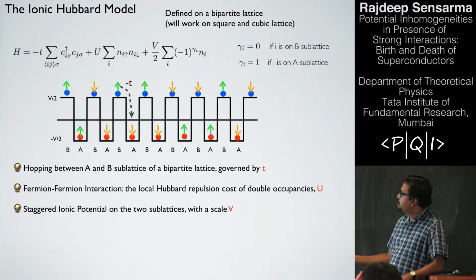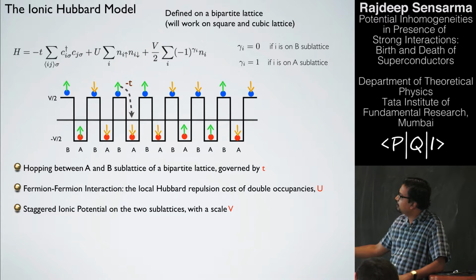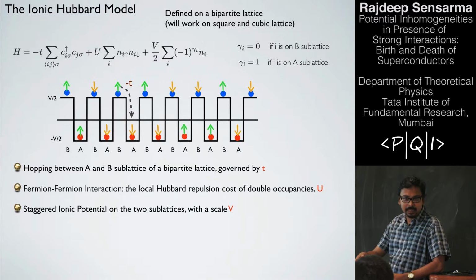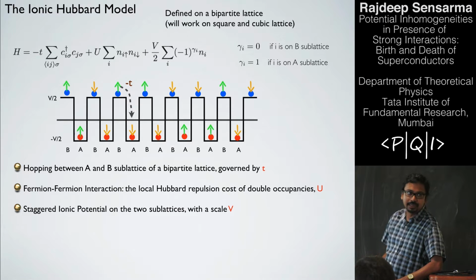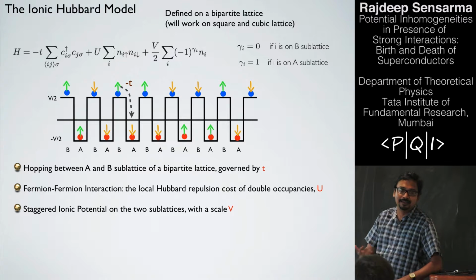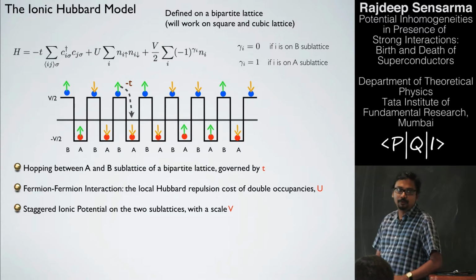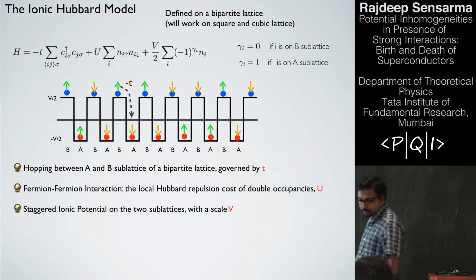On the A and B sublattices, you put a one-body potential which is oscillating, basically. It's minus V by 2 on the A sublattice and plus V by 2 on the B sublattice, let's say. The reason for doing this is that for every hopping across a bond, Vi minus Vj is just V, a constant, rather than a distribution. We would first like to get an answer for what happens in this case before going to distributions and so on and so forth.